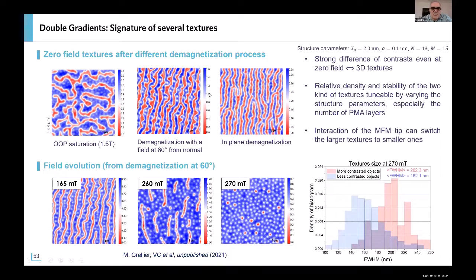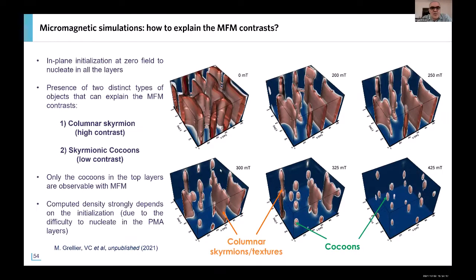Then, when we increase the field from the zero-field imaging, we do see these very nice systems with two objects, and that end up at a large magnetic field with these two things that are in red here, which we believe are skyrmion tubes going through all the multilayers. And then we have this white spot that corresponds to a localized three-dimensional spin texture in the volume of the multilayers. And this is confirmed by micromagnetic simulations that we have performed recently. So these are representations with iso-surfaces. In red, you have an MZ value equal to, in this case, I think, -0.9 or -0.8, and in white MZ equal to 0. So you see that at zero field, we have some worm structure that goes throughout the multilayer.